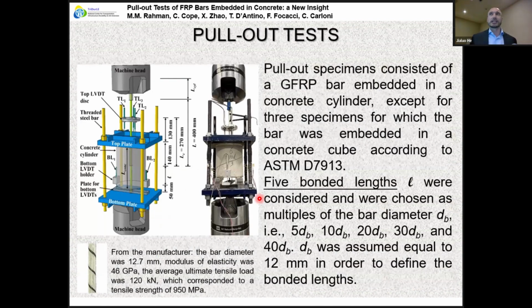We cast cylinders of concrete with the bar embedded with the same idea, but by changing the bonded length. We use 5 diameters as in the ASTM, and for the 5 diameters, we also cast cubes just to make sure that cylinders and cubes were okay. Then we did it also with 10 diameters, 20 diameters, 30 diameters, and 40 diameters bonded length. The bar was a sand-coated bar, you can see it here at the bottom with the wrap of carbon fibers, and the nominal diameter was 12 millimeters.